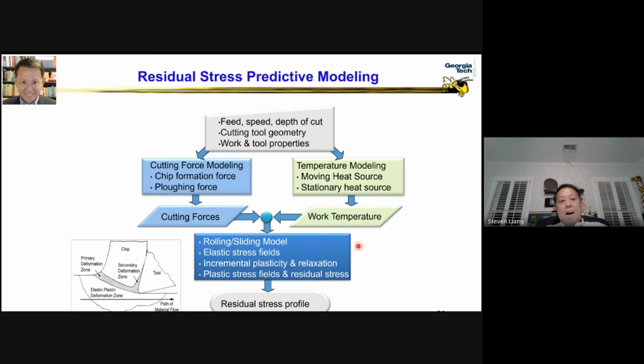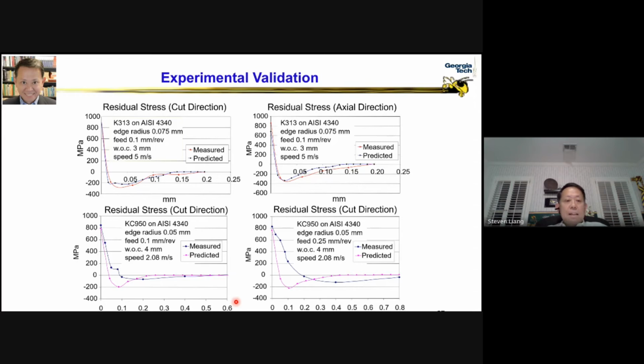So you need to understand how residual stress is created, and we have done a lot of work for the American aerospace industry to look at the mechanical loading, cutting force, as well as the thermal loading in terms of temperature effect, and come up with the kinematic hardening and incremental plasticity analysis to predict the residual stress quite nicely. And this is a line of our prediction in blue color in comparison to our sponsors' experimental work that was done independently in red color, and they turn out to be quite similar in different directions, cut and axial direction, as well as with the use of different materials.